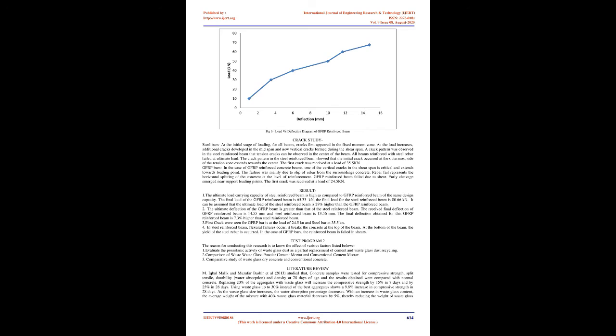It can be assumed that the ultimate load of the steel reinforced beam is 29% higher than the GFRP reinforced beam. 2. The ultimate deflection of the GFRP beam is greater than that of the steel reinforced beam. The final deflection of the GFRP reinforced beam is 14.55 mm and of the steel reinforced beam is 13.56 mm. The final deflection obtained for the GFRP reinforced beam is 7.3% higher than the steel reinforced beam.